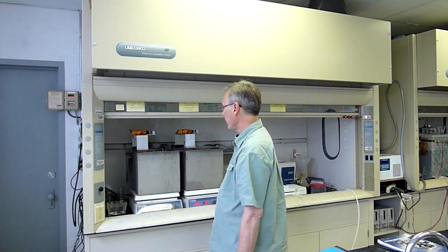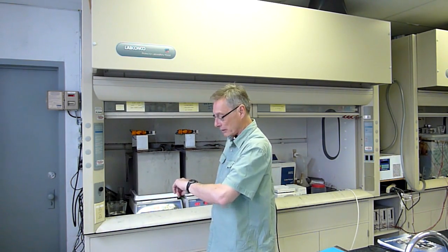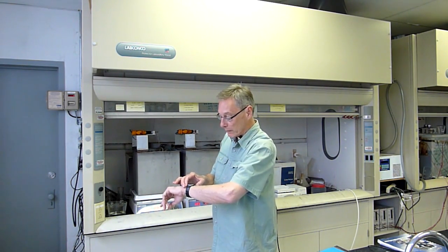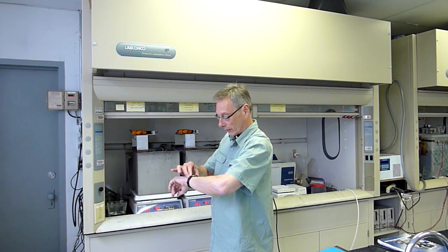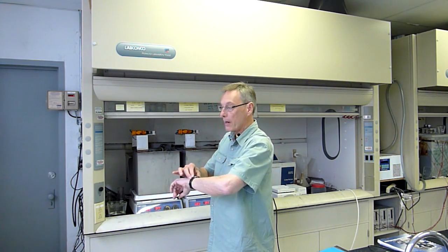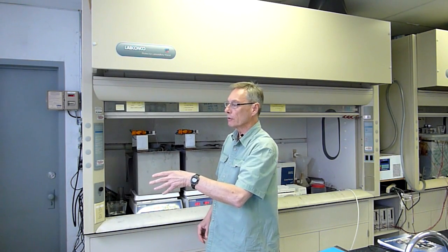And then we'd like to have a fairly heavy layer of gold on this part before we go into the final etching of the aluminum mandrel. So we'll let this sit in the tank for maybe 15, 20 minutes now. And we're depositing this nominal current of 20 milliamps per square inch. We're depositing about 50 micro inches, 50 millionths of an inch of gold every five to seven minutes onto the part.